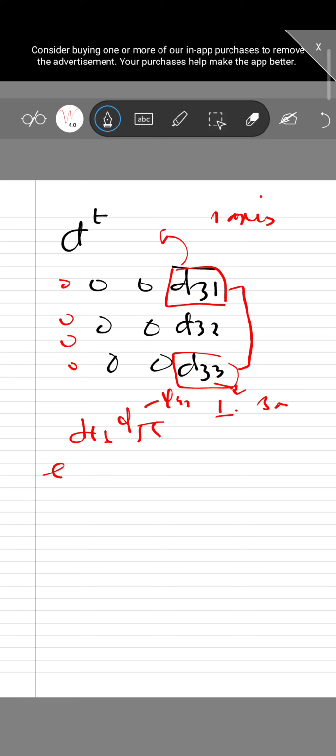And if you write the equation now, the equation in terms of the strain can be written as Eij equal to Sijkl sigma kl. This is the first part, where we are assuming that no electric field has been applied, plus the one where the electric field is applied, which is represented by the inverse piezoelectric coefficient into E.